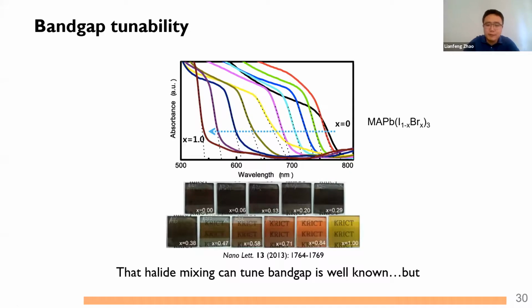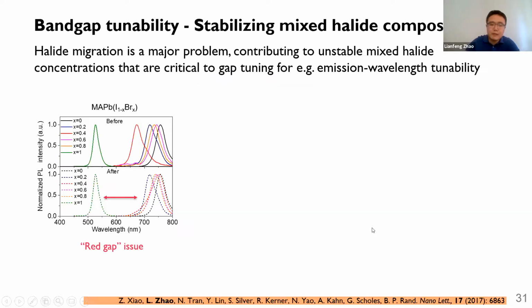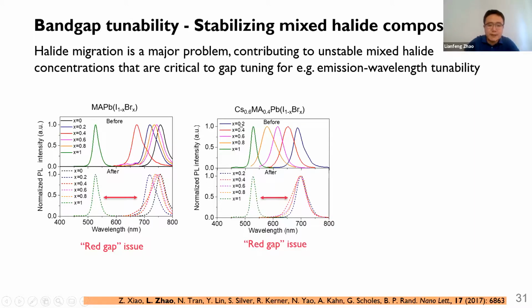It is well known that the bandgap of perovskite can be tuned by changing its composition. For example, by changing the iodide to bromide ratio, we can change the bandgap from green to red. However, if we simply mix things together, there's a red gap. We cannot tune the emission wavelengths precisely. People have reported that adding cesium into the film can help. And indeed, we observed well-tuned emission wavelengths at the beginning, but it's not very stable. After some electrical and optical stress, the red gap issue reappears.